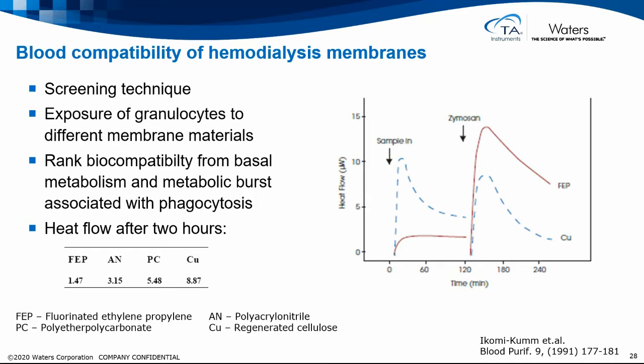Granulocytes are characterized by having a very low metabolic activity when they are exposed to inert materials. And when they are exposed to a material that will induce phagocytosis, they will have a very high energetic burst associated with that. So this test was done by lining the calorimetric ampules with different coatings and then putting the granulocytes into that and measuring the base metabolic heat. Inert material will have less metabolic heat than other material that will activate the cells. So compatibility could be ranked depending on the basal metabolism that you see after 2 hours of exposure.